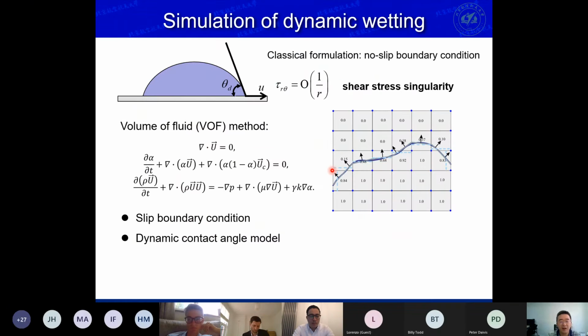And the second part is how to simulate dynamic wetting. It's more complex than the static wetting. Of course, we can use NEMD to simulate a dynamic wetting problem, but the problem is NEMD is time consuming. If you want to simulate the whole dynamic wetting process, it will cost you a lot of time. So an efficient way is to use a continuum simulation method, like VOF, the volume of fluid method. In VOF, we need the continuity equation, the momentum equation, and we also need one equation for the volume fraction. The volume fraction is 1 or 0 for the liquid or the gas region, and is between 1 and 0 for the interface.